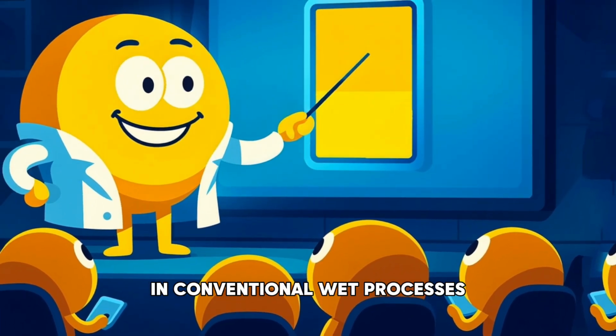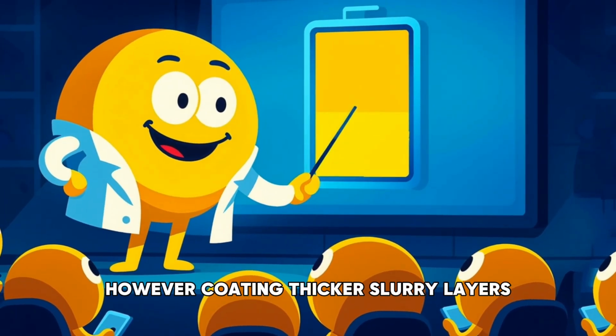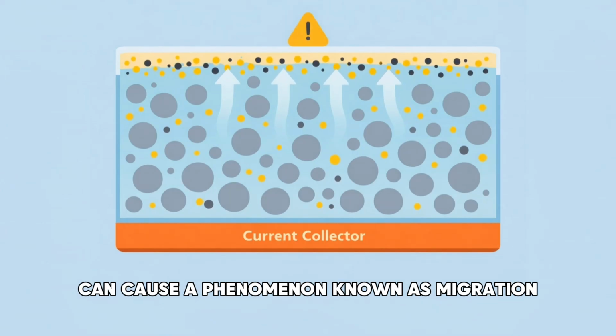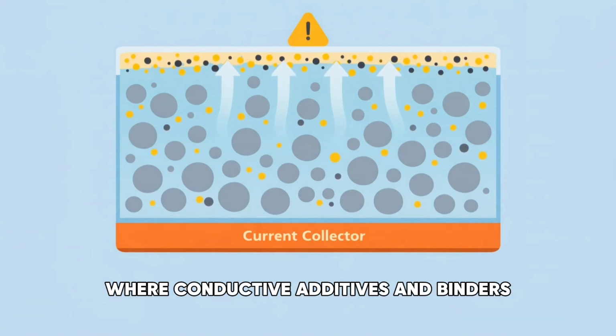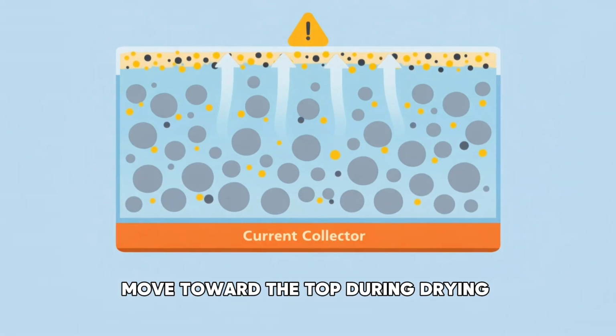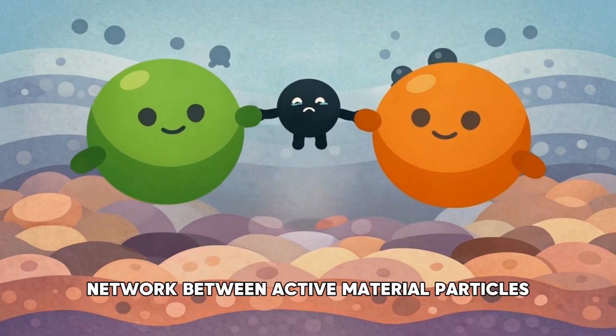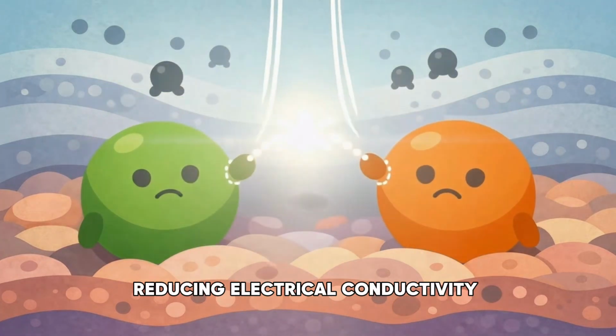In conventional wet processes, however, coating thicker slurry layers can cause a phenomenon known as migration, where conductive additives and binders move toward the top during drying. This disrupts the conductive network between active material particles, reducing electrical conductivity.